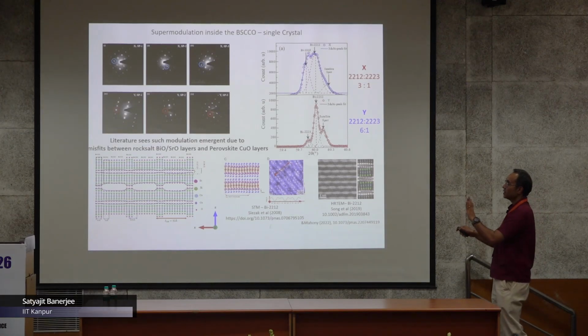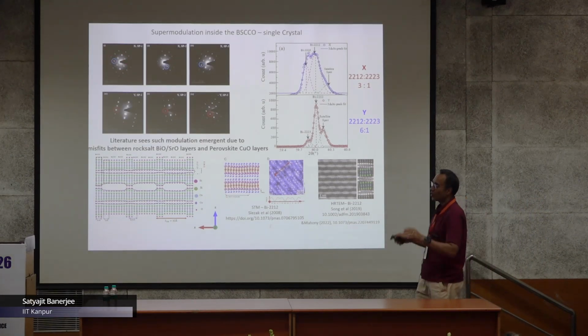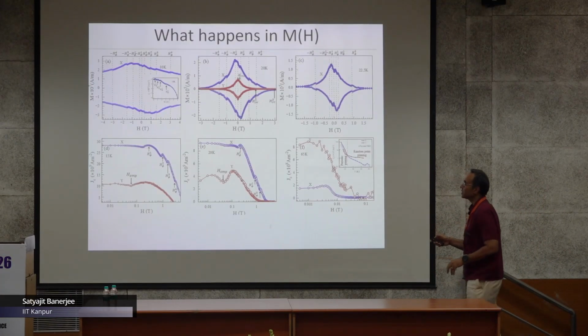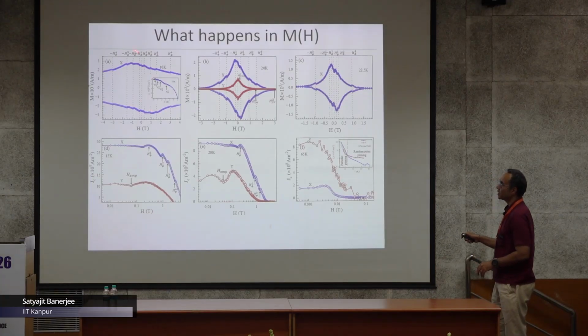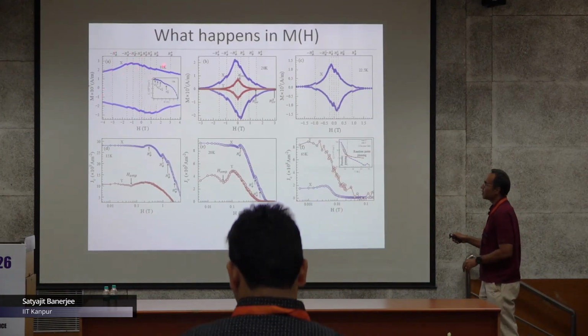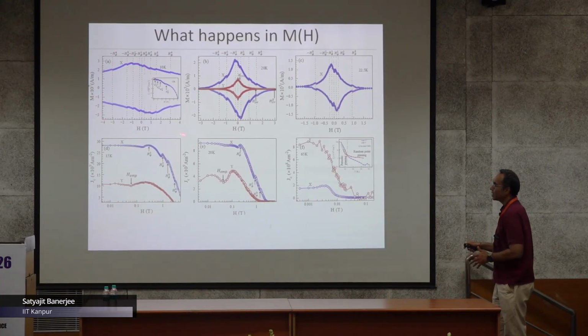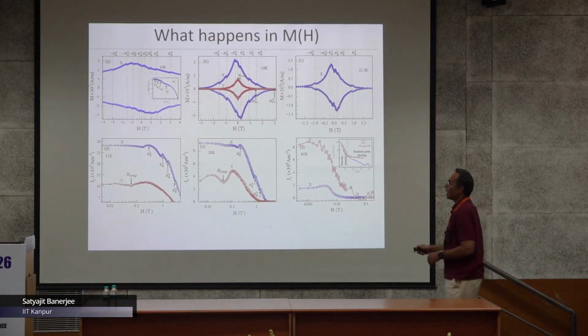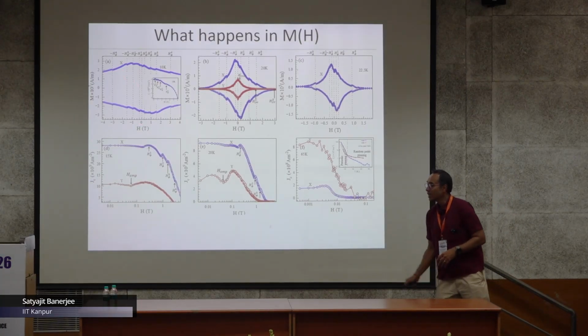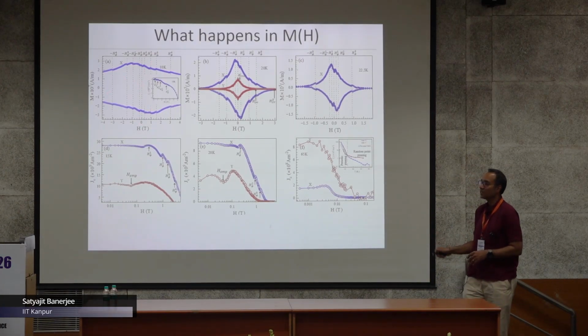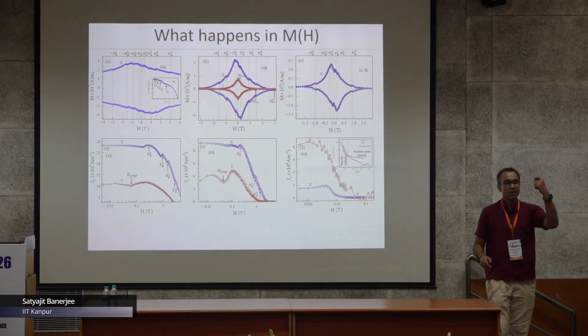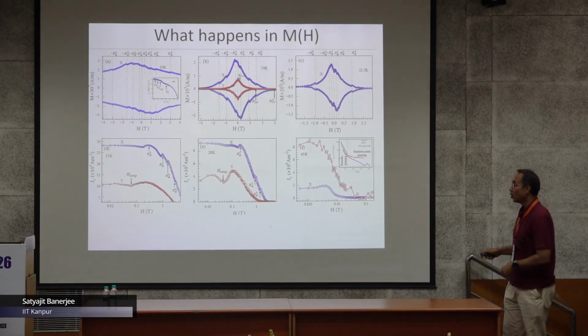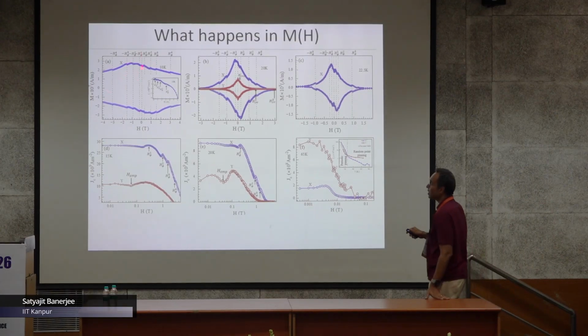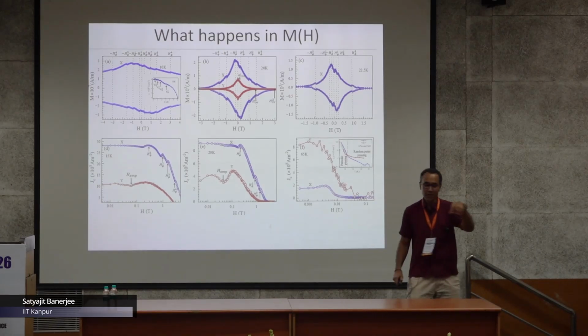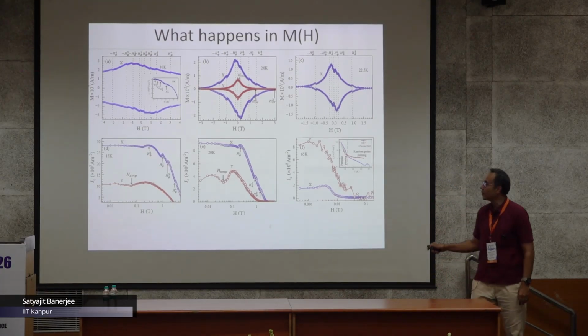Now these are single crystals that we have grown. This is their magnetization - sample X - at 10 Kelvin, magnetization versus field. What you see are peaks similar to what I showed earlier in superconductors with artificially drilled holes, the artificially pinned superconductors with a periodic pattern of holes.